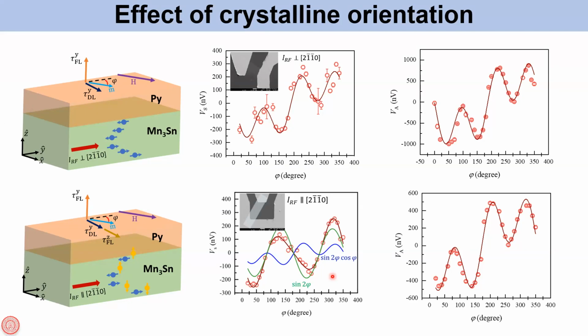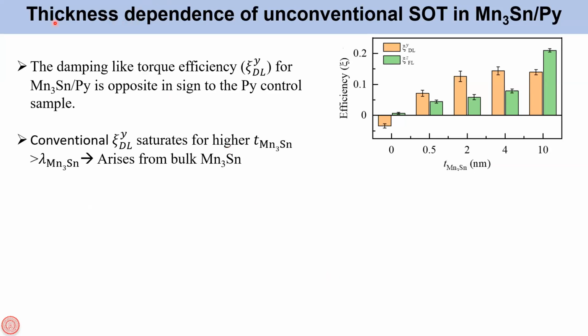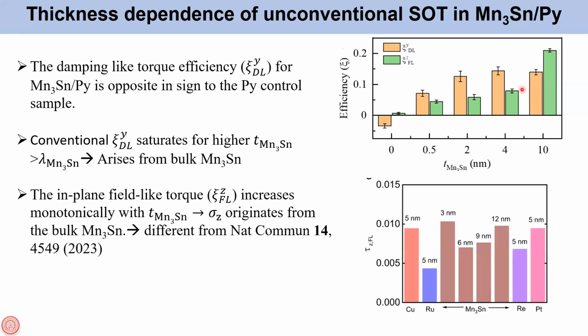And furthermore, we did thickness dependence. In the thickness dependence, we found that there are two components. The conventional torque, shown in the orange plot here, first of all has the opposite sign, and it is present only when Mn3Sn is present. So it indicates that this is a torque coming from the presence of Mn3. And then it increases and saturates, which is a behavior similar to the spin Hall effect. And if you look at the unconventional torque, shown in green, this keeps increasing, with no sign of saturation. So this indicates that this is actually arising from the bulk Mn3.